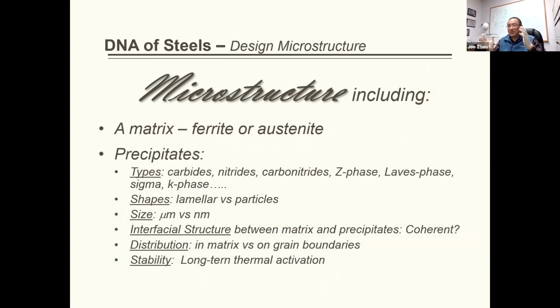So what is the microstructure? When the metallurgist designs a steel, the first thing they design is a microstructure. Microstructure basically is two parts. The first part is the matrix, for steel either ferrite or austenite. When we're talking about creep strength enhanced ferritic steels, the matrix is ferrite. The second part is called precipitates. This part is a little bit complicated, including what type of precipitate: carbides, nitrides, carbonitrides, Z phase, Laves phase, sigma phase, chi phase, pi phase. There's a ton of them.